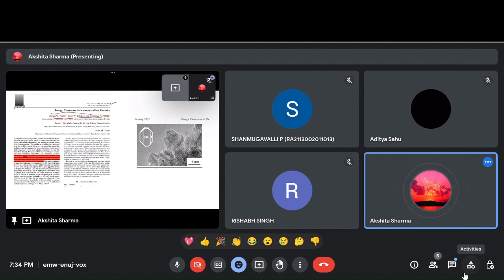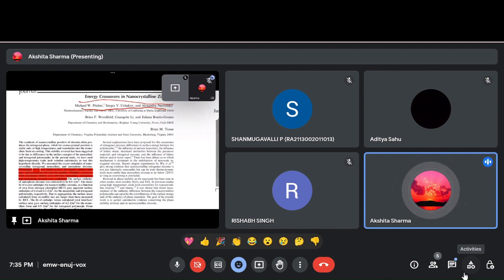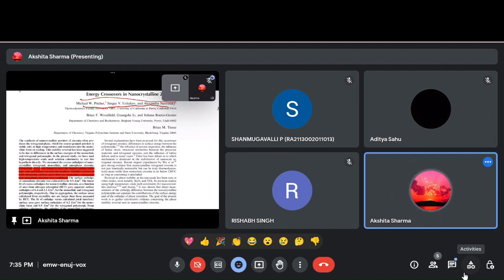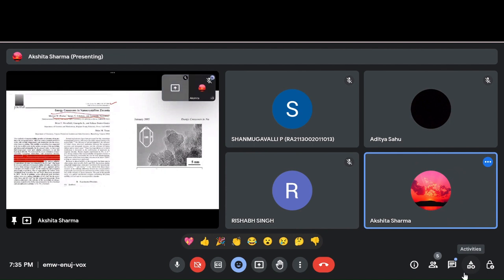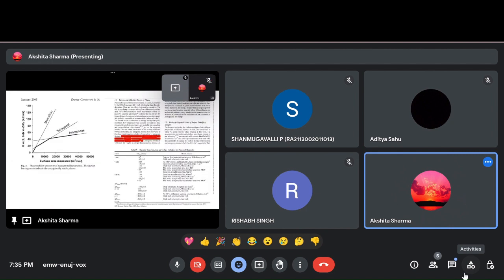Main part of the story is monoclinic zirconia. I have highlighted this part if you're not able to read it properly. Monoclinic zirconia was found to have largest surface enthalpy, and amorphous zirconia has the smallest. Stability crossover with increasing surface area between monoclinic, tetragonal and amorphous zirconia were confirmed. When we went on to the nanoscale level, there was a difference in the surface energies of monoclinic, tetragonal, and amorphous, and it was found that till a certain level monoclinic has the highest surface energy. And I will explain this figure later. First, move on to this part.